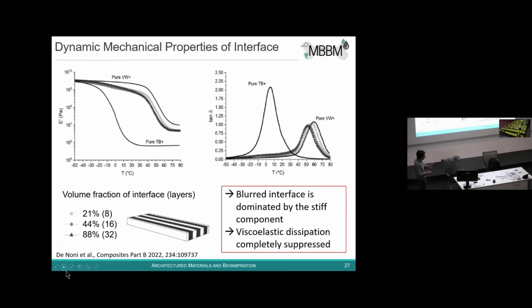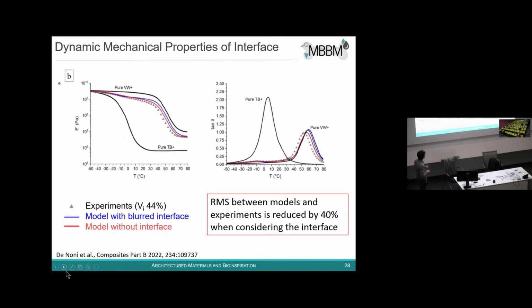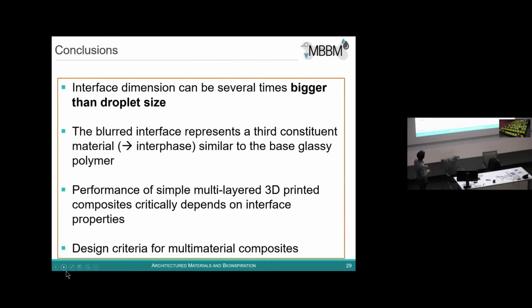So the interface has properties which are strongly dominated by the rigid polymers, and also in the interface itself, the viscoelastic dissipation, which is typical of the soft polymer, is totally suppressed. So that was a little bit surprising. And yes, I think this I can skip.